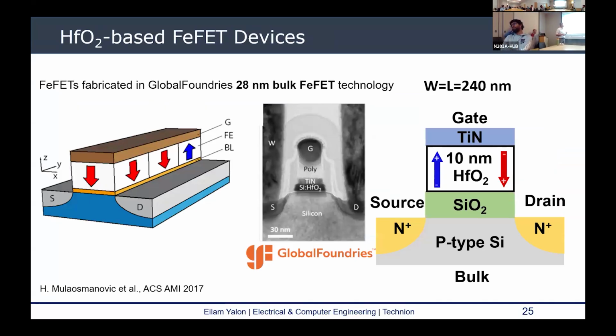For this study, we're using devices that were fabricated by GlobalFoundries in a 28 nanometer bulk FeFET process. So they have an interfacial layer of silicon oxide, about 0.8 nanometers, and then 10 nanometers of silicon-doped hafnium oxide, which is the ferroelectric layer. And so the results that I will show, we're using transistors with width and length of 240 nanometers.